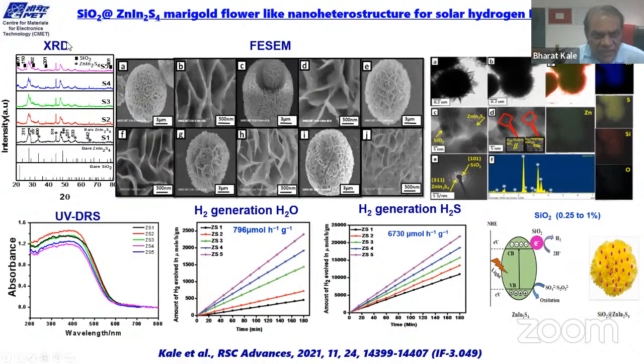So we produced zinc indium sulfide and these petals are decorated with SiO2. You can see that though the structure is retained, all these petals are decorated with SiO2, and it helped a lot in getting enhancement in hydrogen.